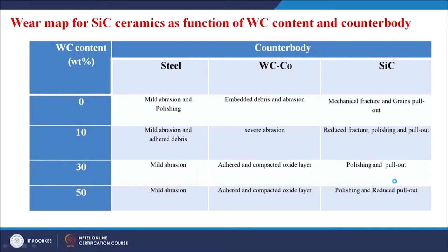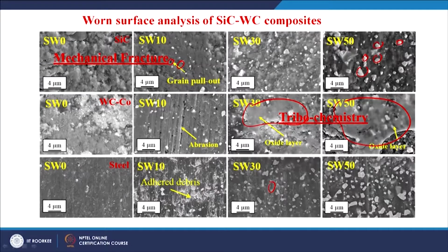So, to summarize the wear mechanisms against different counter bodies as a function of tungsten carbide content, the abrasion and polishing is observed when you do not have any tungsten carbide content and worn against the steel. So, when the tungsten carbide content is increased, you have adhered debris and the debris are entrapped inside the grooves, and against tungsten carbide cobalt, this embedded debris and abrasion which becomes severe abrasion when tungsten carbide content is increased, but as the tungsten carbide content is further increased to 30 or 50%, you can see there is a compacted layer which adheres on the surface.